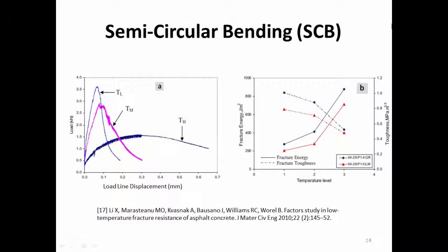So in order to describe the fracture property in this test, they came up with two indexes. One is called the fracture toughness. It's related to the peak load at different temperatures. So as the temperature increases, the fracture toughness decreases because the peak load decreases. The other one is fracture energy. That means how much energy we invest to create so much crack. So they just counted the area below these curves. They found that as you increase the temperature, the amount of energy to create the crack is more. It's because the viscoelastic property is more evident. Right? So you can see this increased trend.